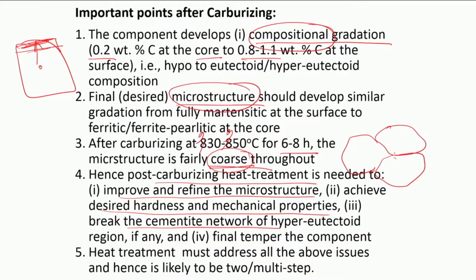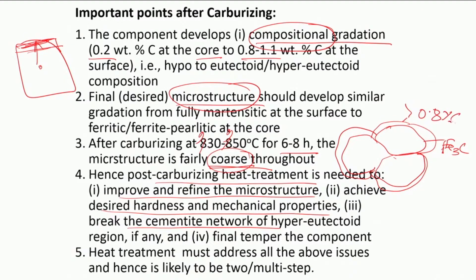Generally if you go to 0.8 and above, or 1 percent carbon or something, then the austenite will be covered by a cementite network. This will be your Fe3C if the composition of the steel is hyper-eutectoid, meaning greater than 0.8 percent carbon. This cementite network is very hard and also very brittle.